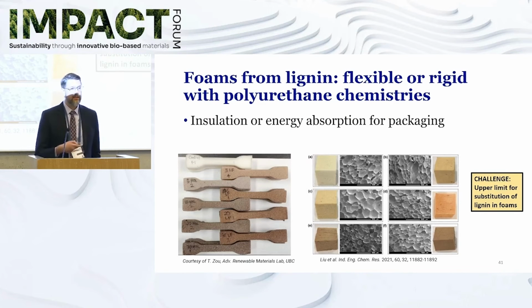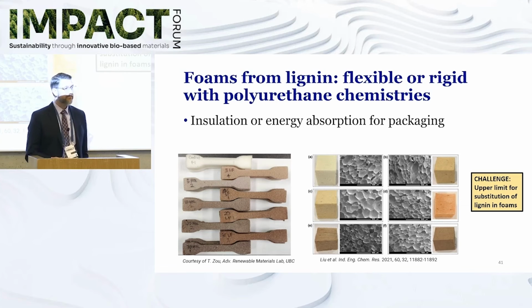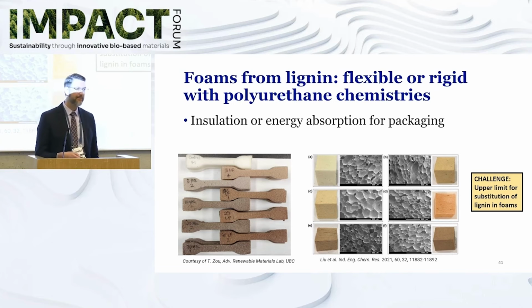There's been a lot of work all around the world on substituting lignin into the polyol component of a polyurethane foam. This can work pretty well in relatively large applications. Polyurethanes are wonderful materials because you can go from a very flexible foam to a very rigid foam, so you can use them for comfort foams to insulation. That's one possibility for lignin, but the drawback is that there's an upper limit in how much lignin you can get into the system without the lignin itself mucking it up.